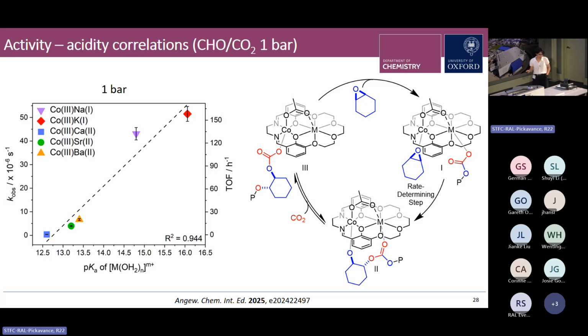So of course there is an alkoxide in this catalytic cycle, but the kinetics plots do not suggest that there is a formal change in rate determining step from epoxide ring opening to CO2 insertion at lower CO2 pressure. But it's still possible that this intermediate becomes increasingly important in governing the relative rates across the series, because you bias your CO2 insertion equilibrium towards the alkoxide at lower CO2 pressure.